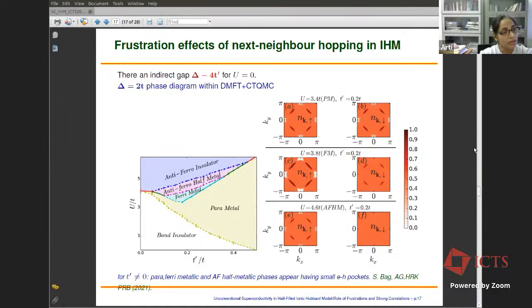None of these ferrimetal and antiferromagnetic half metal phases have ever been seen in the half-filled Hubbard model in the presence of second neighbor hopping. So these are the specialty of the Ionic Hubbard model, and it happens because of the imbalance between the two sublattices. So what are the features of this correlated metal, ferrimetal and half metal phase?